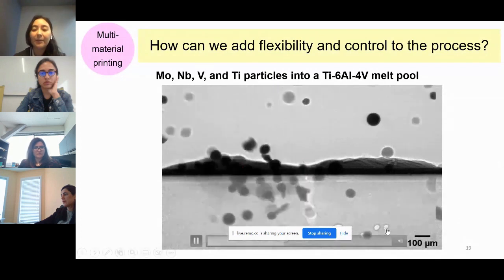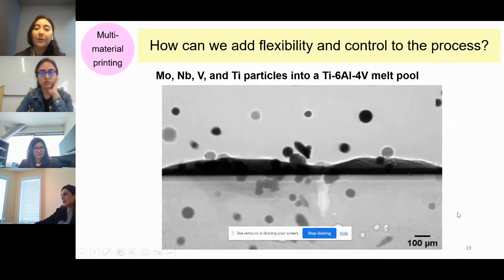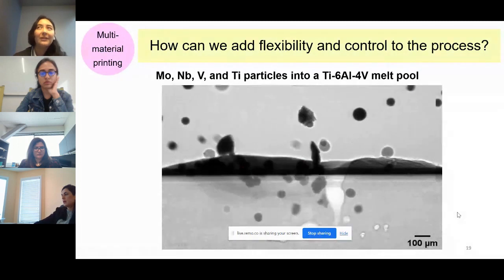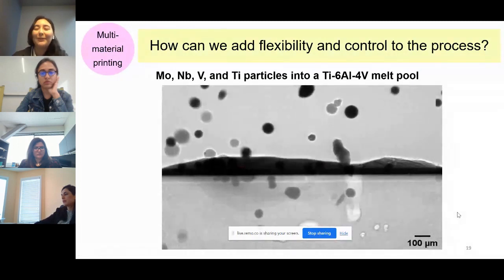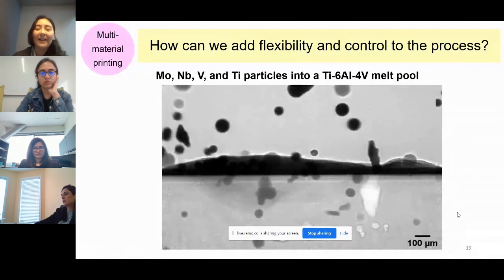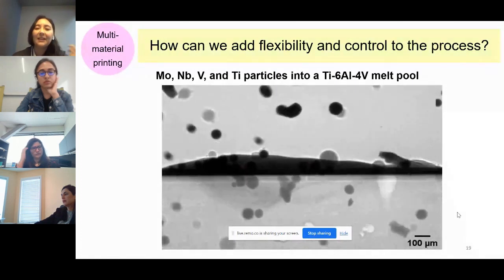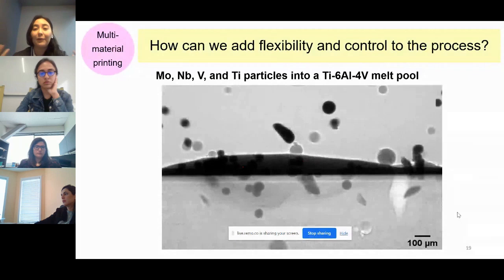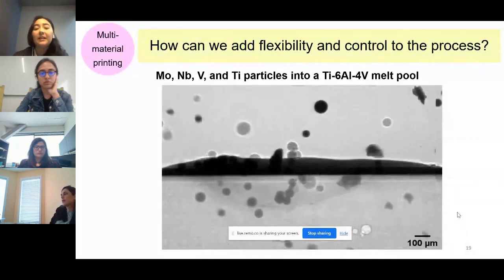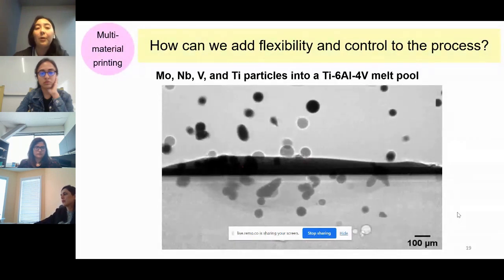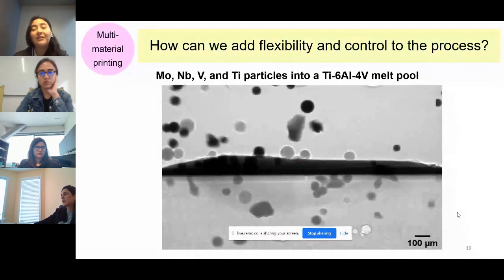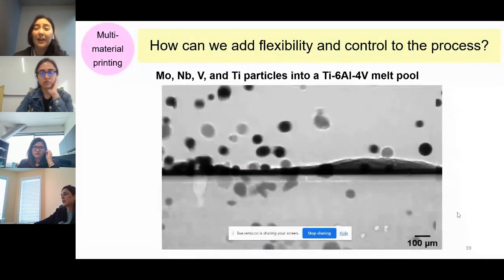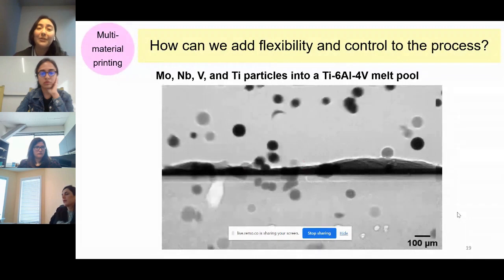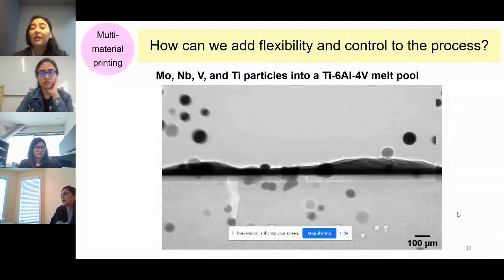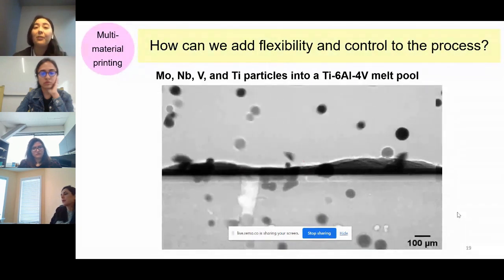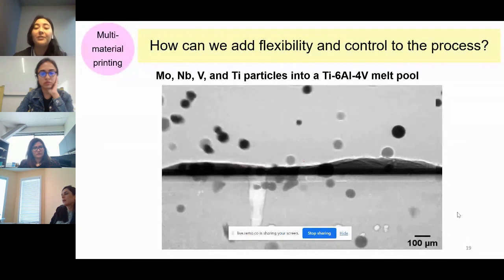And if you can probably see in the bottom there, these little white bubbles, those are pores. We didn't know how to control this. It was just, let's try and see what it looks like during the process, if we can actually melt them. But we could actually see we're creating these bubbles, these pores. Sometimes, actually most of the time, you don't want those pores, but if you're lightweighting material, maybe you do want air bubbles or air pockets that are far enough away from the surface so they don't cause issues when a part is in use.